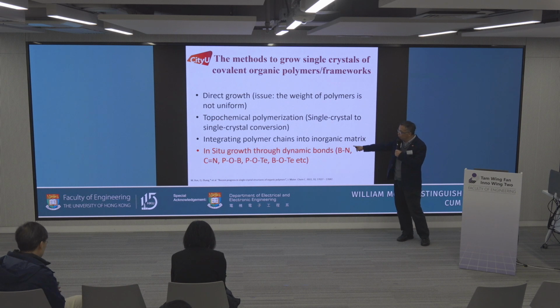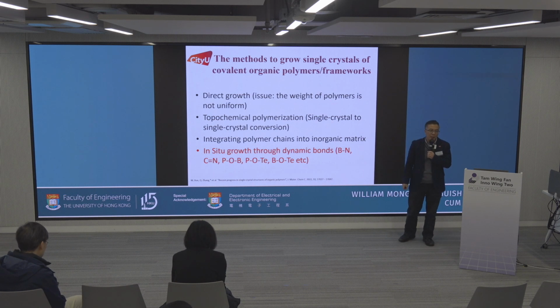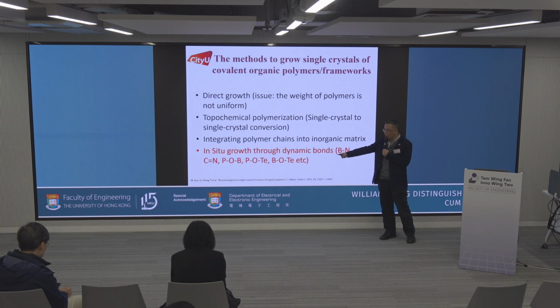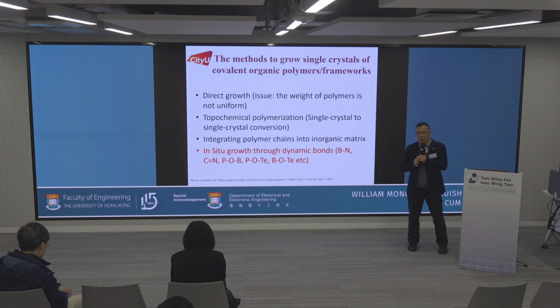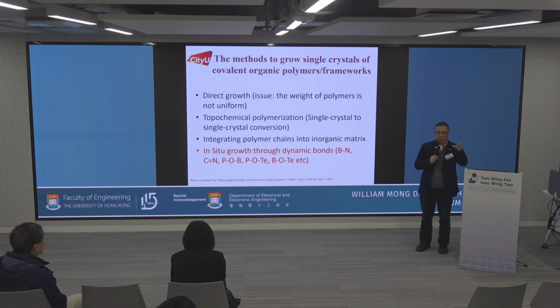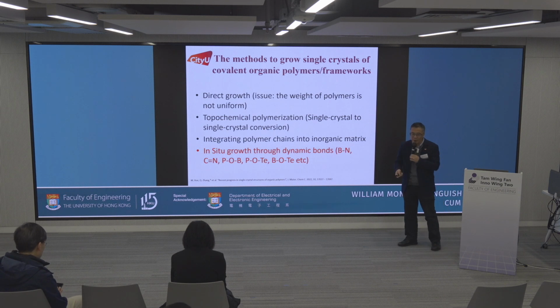Okay. So for today's talk, I'm going to talk about our method. This method is used by a lot of groups, and it is a very popular method. We try to use dynamic bonding to form the single crystal. The reason is that when we grow the single crystal, the bonding arranged in space may not be perfect. So we need the bonding to dissociate again and then regrow. So this dynamic bonding is very, very important.